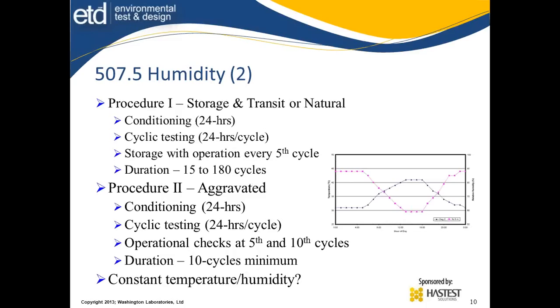The humidity has a couple of procedures. The storage, transient, or natural humidity cycles, which calls for a conditioning period of 24 hours. Get it to a stable state before starting the cyclic testing with 24 hours per cycle. The storage with operation test, if you've elected to do that, the operation is done every 5th cycle. So it goes into storage mode, and then an operational test is done every 5th cycle. The duration is 15 to 180 cycles.